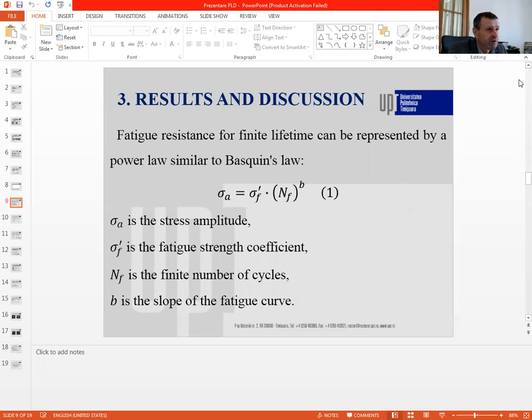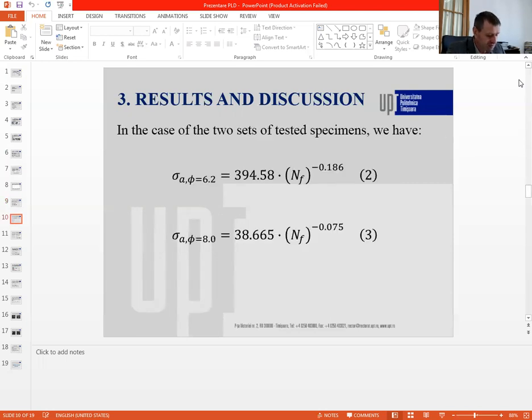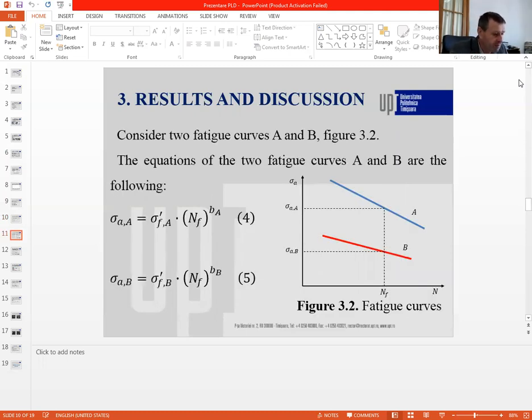Fatigue resistance for finite lifetime can be represented by a power law similar to Basquin's law, see equation 1. In this case, for the two sets of sample tests, the equations of the fatigue curves are expressed by relations 2 and 3. For correlation, we consider two fatigue curves characterized by their equations 4 and 5.